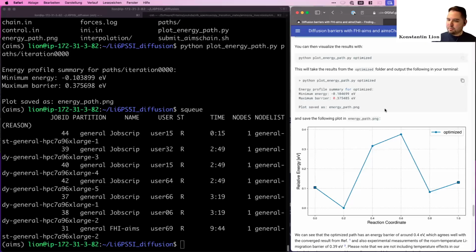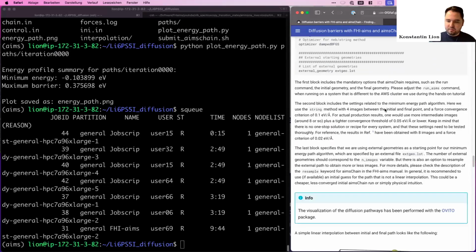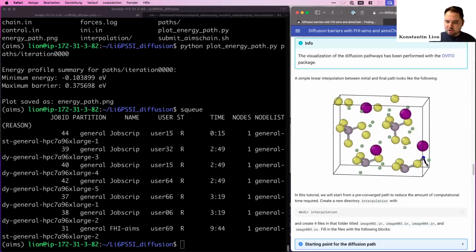And then how to find the minima points? In this case, this was done manually. You start with a normal crystal position that you have. Then you move the atom to there, and then you just relax both structures, right? You relax the first structure in a separate calculation, and the other structure in another calculation. And that's how you find the minima. This is a choice, of course. The user has to say what kind of minima you want to sample. I hope that's good enough of an answer.